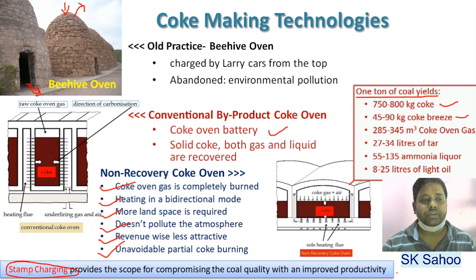to increase the bulk density by about 30 to 35%. The briquette dimension is almost the same as that of the chamber of the coke oven plant. Then it is pushed into the coke oven. As the bulk density of the coal has been increased, the coke formed will be much stronger. This technique provides the scope for compromising the coal quality, that means utilizing to some extent non-coking coals. But stamp charging improves the quality of the coke by about 10 to 12%. Productivity will be increased by stamp charging inside the coke oven plants.